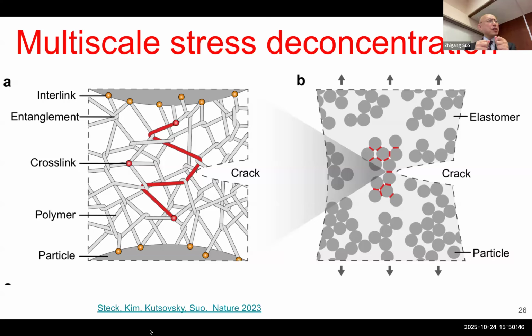A new story for why toughness is even higher than contributed by long chains. We said it's the following. Here is a hard particle, in our case a silica particle, glass particle, nanoscale particle. In between two particles, there is a layer of rubber, then another particle, another layer of rubber. It's well known in the rubber industry that if your particle loading is beyond a certain percentage, the particles will cluster. In the sense that, on average, some particles in a group will be closer than other particles. In between the particles, you still have a layer of rubber, but that layer becomes very thin.